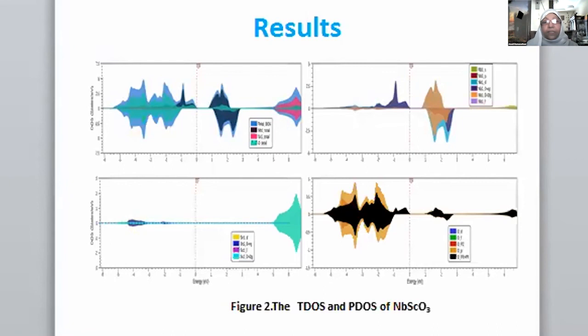In this, I have shown the total density of states and the partial density of states for the different constituents. So in the first graph, on the first top part, left top one, we have the total density of states for all the elements. And you are seeing basically the gap, which is there, near the Fermi energy, that's the line over there. I don't know, can I use the cursor? Yeah, okay. So you are having this line here. This line is the Fermi level, exactly sitting around at the Fermi level. We are having the spin up showing that the band edge is very close to the Fermi level there. And here, this is giving an indication of the gap in the spin up or majority channel, and in the minority, we are having the wider gap.